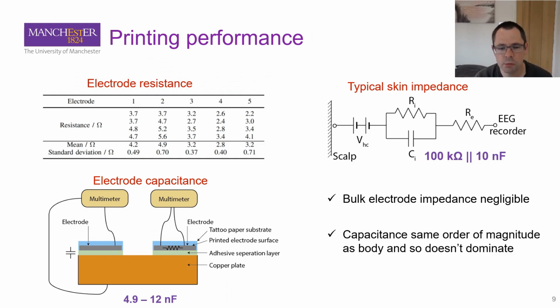So we measured the performance of our electrodes electrically, in terms of the resistance of the printed silver layer before we put the adhesion on, and that is robustly below about 5 ohms. The resistance of a connection to the body is about 100 kilo ohms or so, and so it's negligible in comparison. We also measure the capacitance by connecting the electrodes to a copper plate, and here we get about 10 nanofarads or so of capacitance. And that's about the same as the capacitive connection that we typically get when connecting to the body. And so it's not dominating, it's going to roughly halve the total capacitance that we get compared to conventional EEG electrode monitoring.